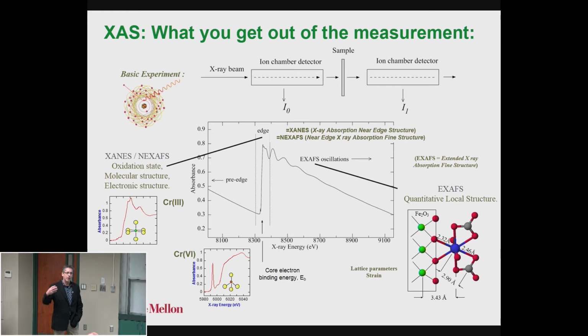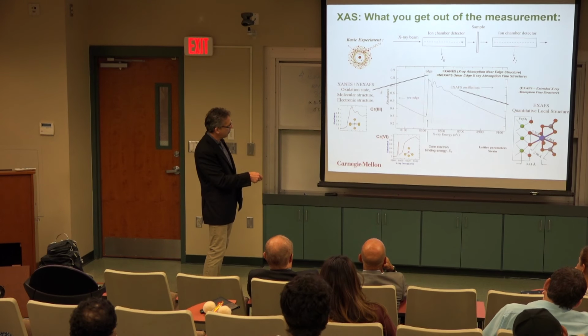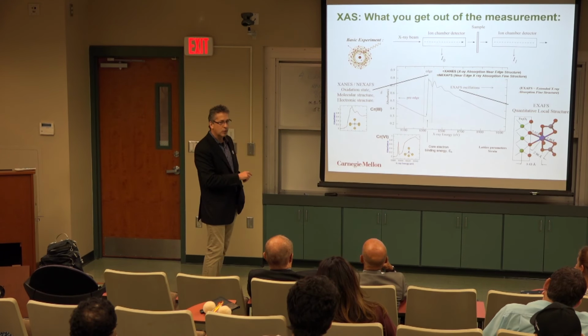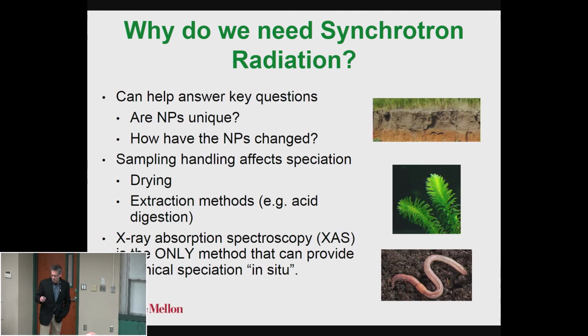Now, if it's a nanomaterial, I can also know that it's a nanomaterial based on its properties. So I can use these to identify nanomaterials in samples. I can use them to identify if the nanomaterial has changed, because if it's changed, I'll know the atoms around it have changed. So this is basically what we do. We either look at the XANES region here, and you can see here's an example of chromium 3 versus chromium 6. That's the XANES region of chromium 3, that's the XANES region of chromium 6. Totally different. So you get this fingerprint, you can identify things pretty easily with this method. And I'll tell you why it's really important in a second when you have mixed metals in a sample.